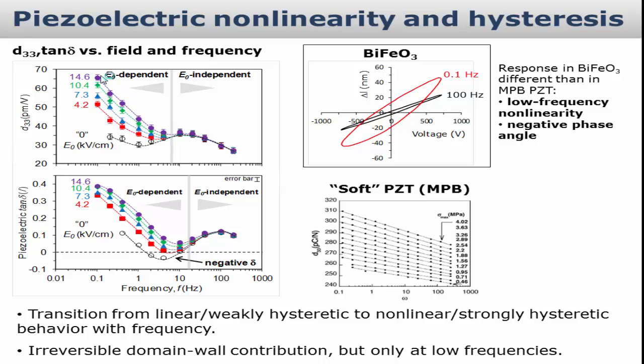Now, what is the main difference? This is also happening in PZT, we know, but the main difference is that this piezoelectric nonlinearity with hysteresis somehow manifests differently than in PZT. For example, in PZT, you typically measure nonlinear responses in the whole frequency range, in a fashion like seen here with this logarithmic dispersion. In BiFeO3, we see that this nonlinearity sets in only at very low frequencies.